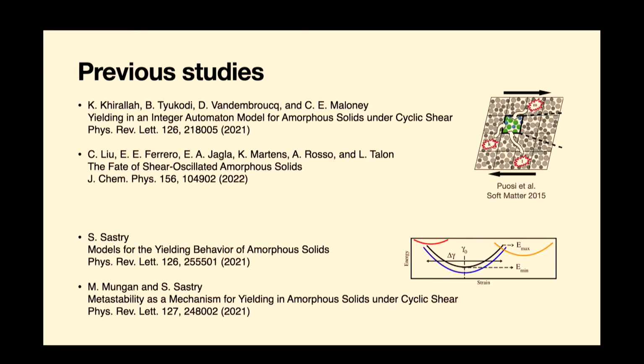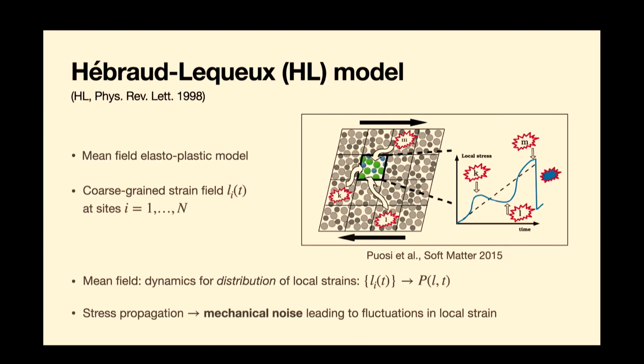They're meant to indicate that if something plastic happens here, or rather this is drawn the other way around, if you look at this block, you have plastic events happening here, then that will affect what's happening in this other block. So it's one of the earliest models of that type, for mean field athermal elastoplastic descriptions, the so-called Hébraud-Lequeux model. This looks at this coarse-grained strain field that I've just described. Let's call these local strains l_i in each of these blocks, which I've labeled by i. Okay, and then as it's mean field, rather than looking at these individual l_i, it looks at the distribution of these strains across the system. Okay, and so it tries to represent what I've described, these local plastic rearrangements plus propagation of these perturbations. When something yields locally, it perturbs the stresses and strains elsewhere in the material.